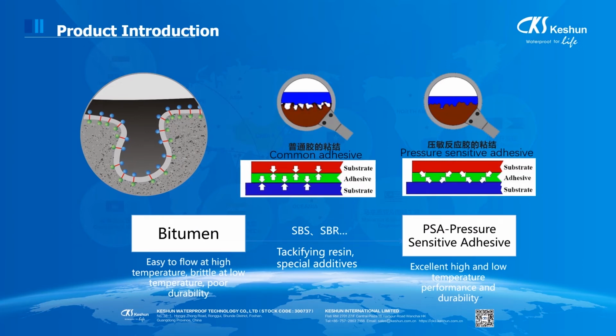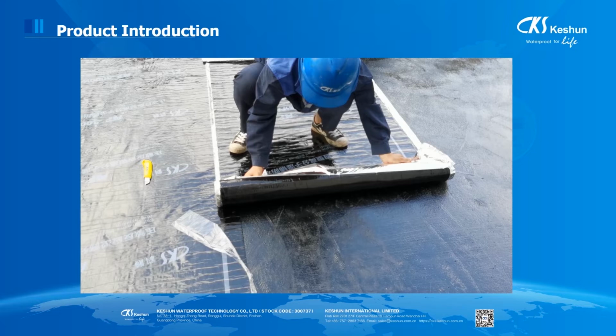Then let's see the adhesive layer. Common bitumen is easy to flow at high temperature and brittle at low temperature, and also has poor durability. After we add additive resin, SBS and SBR in it, we can make the bitumen have excellent high and low temperature performance and durability. Our APF-3000 peeling strength is as good as SBS membrane. When we use torch membrane, we always have a headache about the overlap bonding. But APF-3000 is different. Both the bottom and the surface have the adhesive layer, so it is more reliable at overlap bonding.